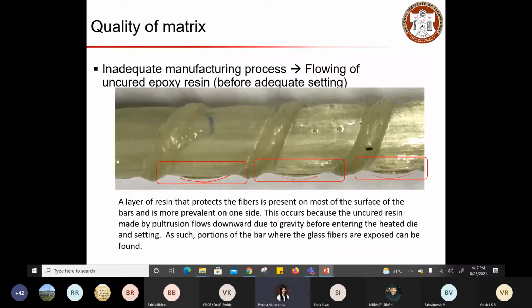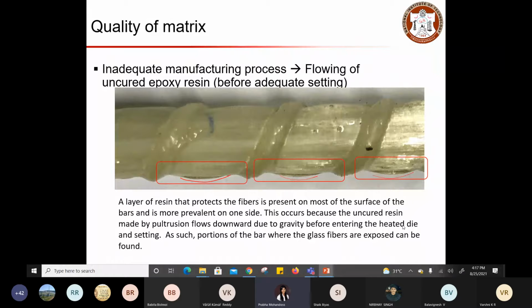This occurs because the uncured resin made by pultrusion flows downward due to gravity before entering the heated die and setting. As such, portions of the bar where the glass fibers are exposed can be found. Okay, so in such cases, this becomes your weak region, and some of the glass fibers may get exposed because your epoxy is not adhered to the surface.